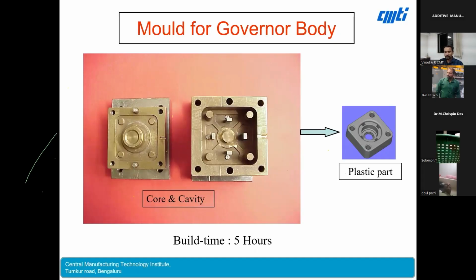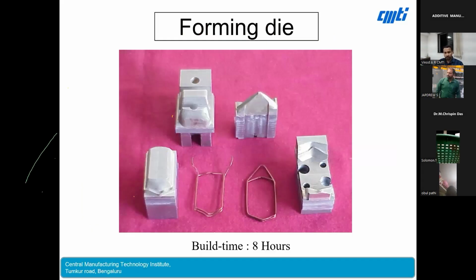This core and cavity was printed in one go. Within 5 hours it was fabricated. Likewise, you have several examples, for instance forming dies. This copper foil coil was transformed from one shape to another using this die. This die was manufactured by this process within 8 hours.